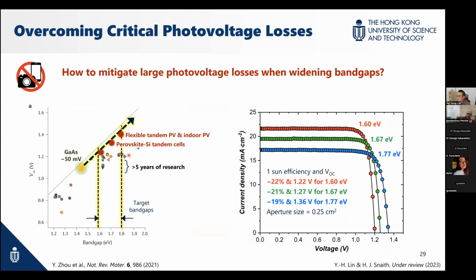So, we have done some special treatment to the perovskite film. It's basically a top surface treatment. Sorry, because the work is still under review, I'm not able to disclose the molecule. But just like you have perhaps read in some papers regarding perovskite, it is about how to improve this kind of photovoltage loss. We also achieve some very impressive values, especially for 1.6 electron volt, this kind of band gap, which will be the middle cell for triple junction perovskite cells. This 1.67 electron volt is the perovskite for perovskite-silicon tandem. And this 1.77 electron volt will be the perovskite for perovskite-perovskite tandem solar cells.